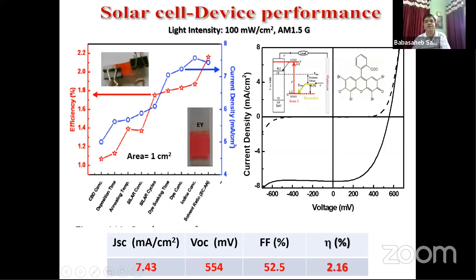Here you can see the current-voltage characteristics for the solar cell, and you can see that the efficiency we have reached is about 2%. For silicon, gallium arsenide, or CdS, CdTe type solar cells, the efficiency is very high, no doubt, but the cost is very high. For this type of solar cell, although the efficiency is less, the cost is drastically less than the silicon type solar cell. Where area is not a problem, you can use this type of dye-sensitized solar cell.